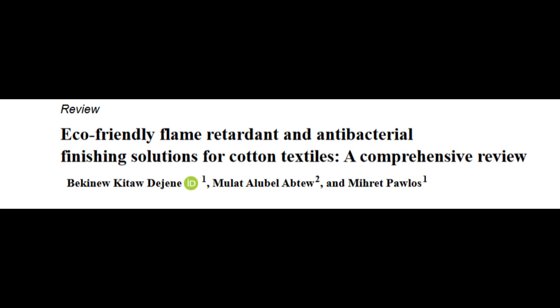Okay, the ultimate goal. Dual functional agents. Flame retardant and antibacterial in one treatment. That's the holy grail for efficiency, yes. And interestingly, some FRs do have inherent antibacterial activity. Potassium alginate with PHMB was one example. But chitosan seems like the star here, too. It really does. Chitosan combined with phosphorus-containing flame retardants is a common and effective strategy for hitting both targets. Using waste shrimp shells makes it even more sustainable.